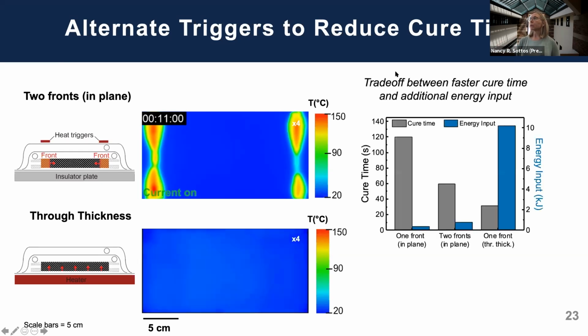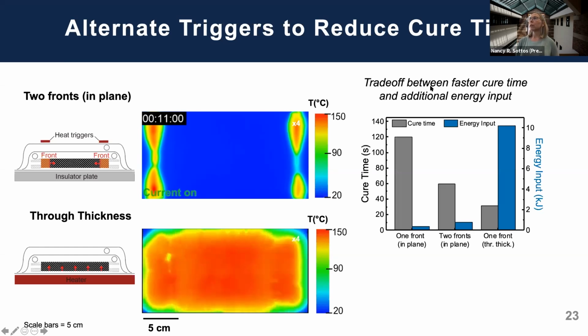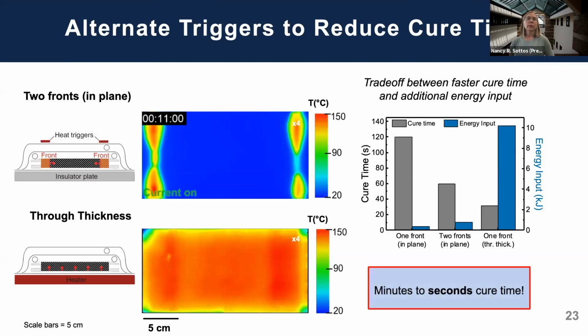And if we compare these, really there is a bit of a trade-off between asking for a faster cure time, because we need to put a little more energy into, say, this through thickness case. What I plot here is the cure time for each case, the one front, the two front, and the through thickness material. And you can see the cure time is coming down from 2 minutes to 1 minute to approximately 30 seconds to cure a composite panel. And then corresponding on the right-hand side is the energy input. So one front is the least amount of energy, a very small amount of energy, twice the energy for two fronts. And then, of course, to trigger it with this heater underneath it requires a little bit more energy, nothing close to an autoclave, but still significant compared to the other methods. And so we've gone from minutes to seconds in cure time, but at an energy penalty.